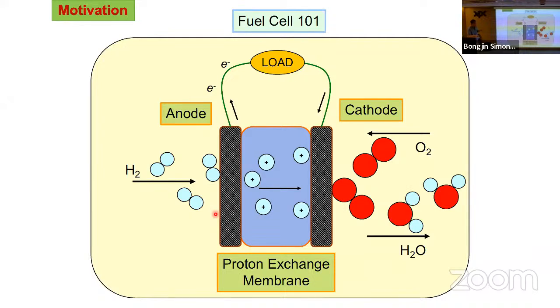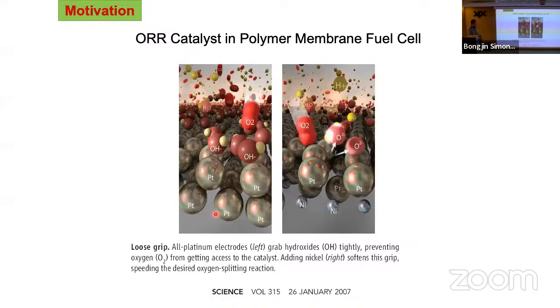And so the idea is you need to improve the reaction process. And on top of that, it's very expensive. So you want to actually reduce the amount of the platinum. So the idea is replacing some of the platinum with a cheaper transition metal, for example, cobalt or nickel, then maybe you could help a little bit better. So this was the very big driving R&D effort during the Obama administration. During the Obama administration, the fuel cell, they were really pushing it.